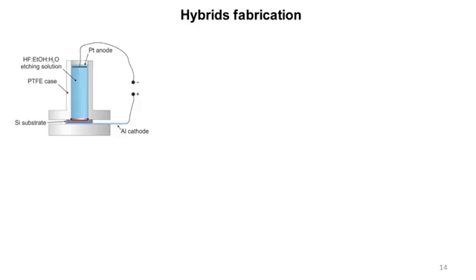Fabrication of porous silicon photonic crystals was performed using the procedure of the electrochemical etching of monocrystalline p-type silicon. Etching was performed by means of a self-made etching setup. The mixture of hydrofluoric acid and ethanol was used as an etching solution.